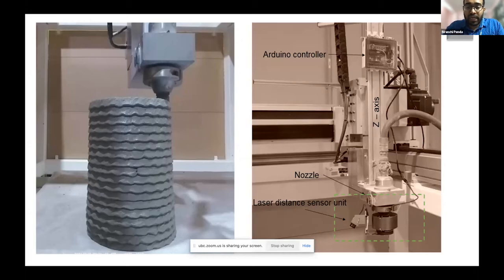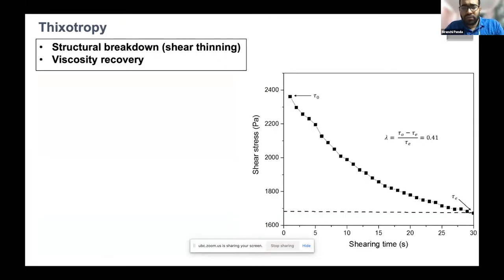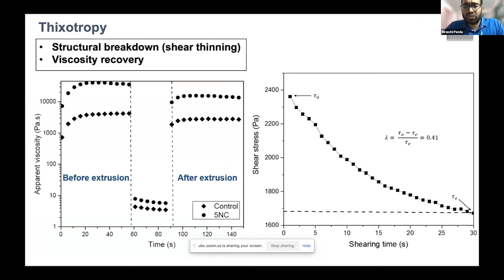So during printing, we have added laser sensors to track the layer height deformation, and all this information we store in a cloud database. And then with the help of an AI network, we have optimized the parameter settings so that during printing, if the material senses deformation, then the parameters are automatically adjusted so that you are not going to see any collapse during printing. So from the material point of view, we have done some thixotropy characterizations.